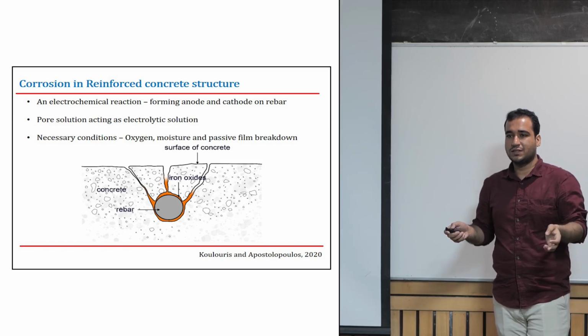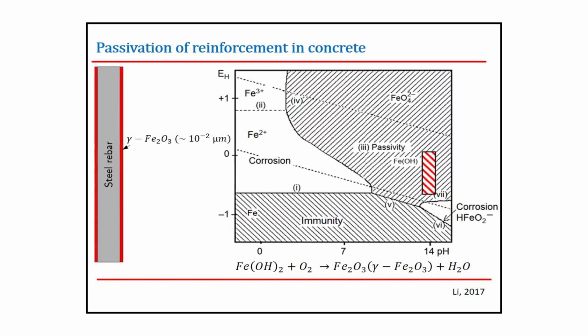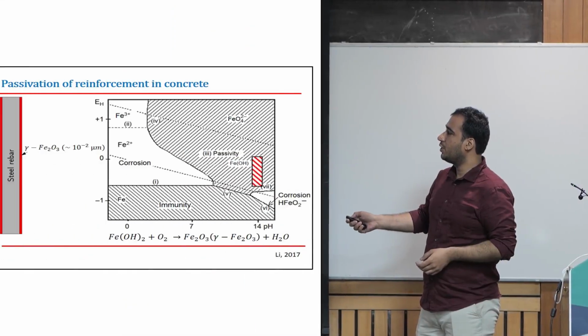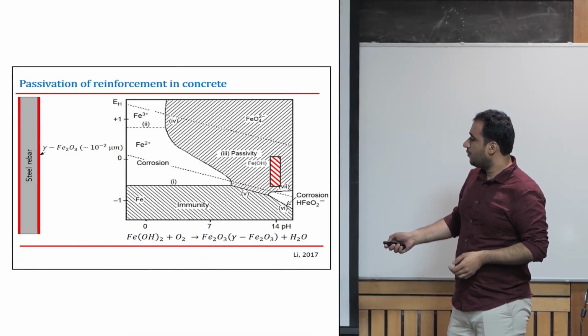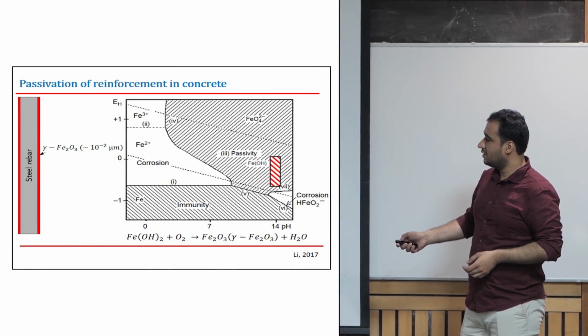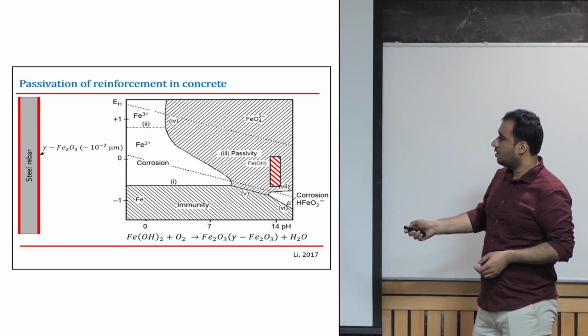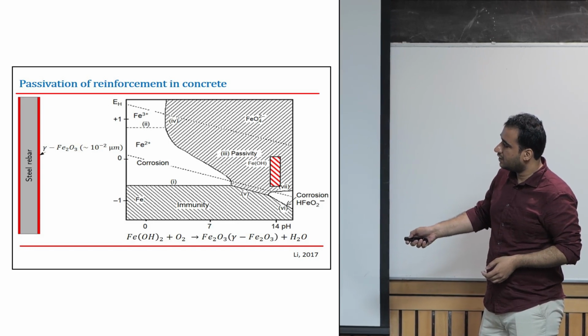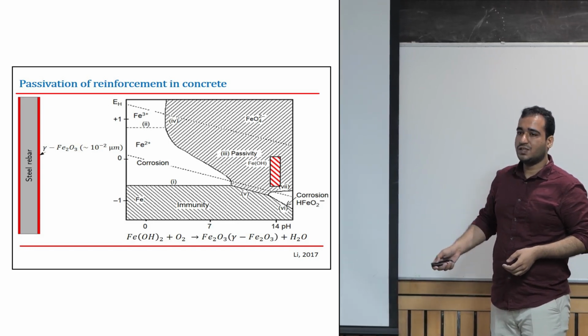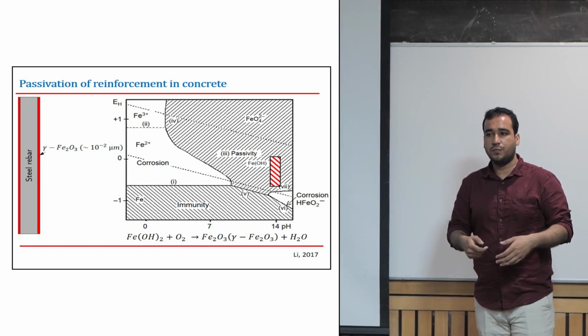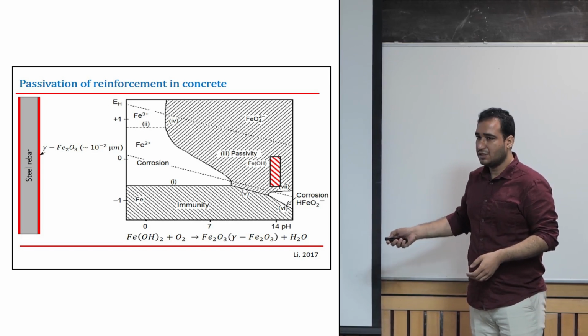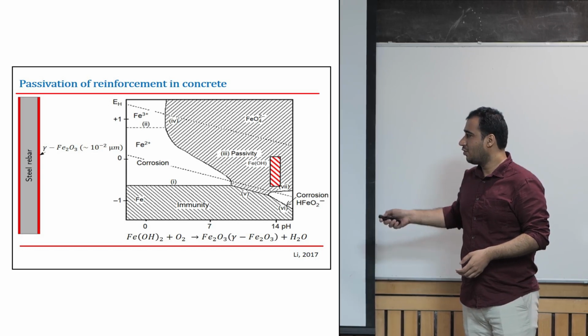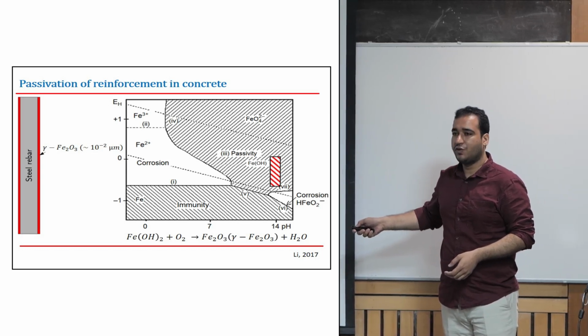Most of you have heard about the passive film, I guess. I hope so. If not, here is a brief slide about the passive film for you. In concrete, we have a pH of more than 12. This is a Pourbaix diagram for iron. So when you increase the pH, there are different zones where iron can be stable, immune, or corroding, or in a passive film stage. In concrete, we have a pH of around 12 or greater. So in this range, at this potential, you see there is a kind of passivity layer. This is a layer that forms around the rebar, gamma Fe2O3. That's a protective film which doesn't allow the rebar to corrode, specifically under these conditions. Luckily, this is the case with our concrete. We always have it in a passive zone unless somehow we destroy this film.